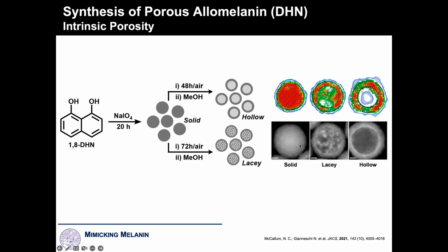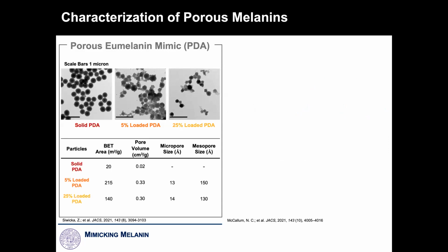This is now an electron micrograph of the materials. We can make them like solid bowling balls. We call them lacy particles, where they're kind of ball spheres with some pockmarks inside them. And then we can make them like ping pong balls, completely hollow inside. And this student wondered, along with the other ones, how porous are these materials? On our melanin mimetic, which is the one I described on the template, these are fairly porous materials. The typical surface areas you expect for something like this, which is not particularly porous, are on the order of tens of meters squared per gram.